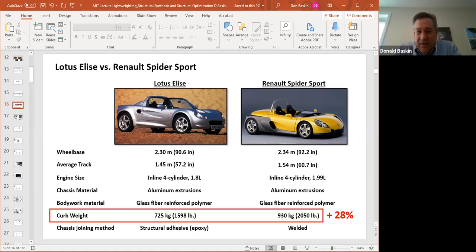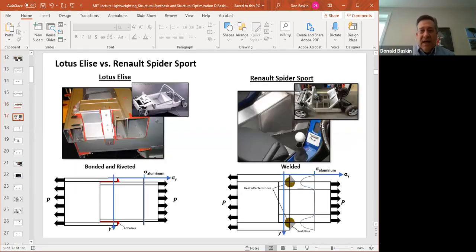It comes down to the way that the structural members are joined. When you take a precipitation strengthened aluminum and you weld it to another piece of precipitation strengthened aluminum, you get a substantial decrease in strength because you get coarsening, or you lose your heat treat in areas that got hot from the weld. We call that the heat affected zone. And in order to compensate for this weakness, it's necessary for the design engineer to increase the wall thickness of the structural member to compensate for the lower strength that's created from the heat affected zone, or from the heat exposure.